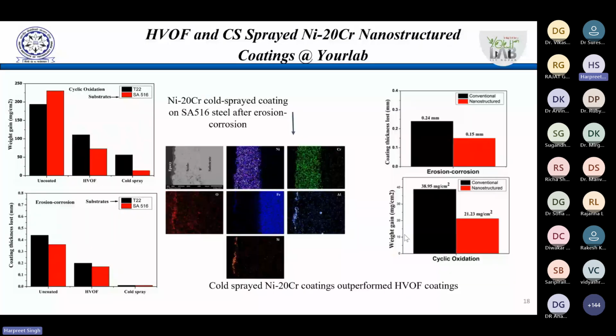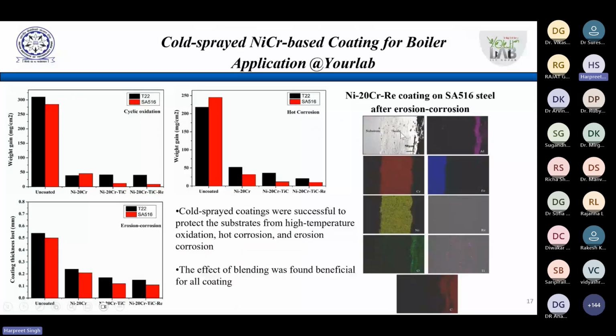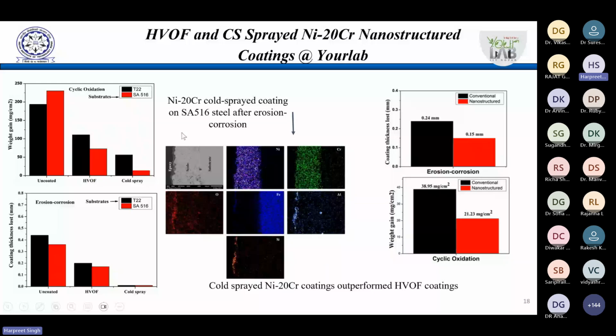Similarly, another study which we did, this is done by in fact Dr. Manoj Kumar, another PhD student. So what was done here, basically we have developed nanostructured coatings. Here the grain size of these coatings is in micron size, but then here we have reached nanostructured coatings, basically by playing with the powder chemistry and morphologies, right? So there was a strategy that we made this powder. In fact, this is very innovative work.